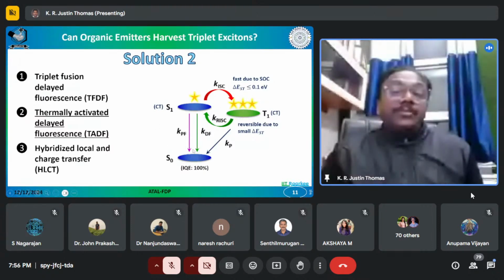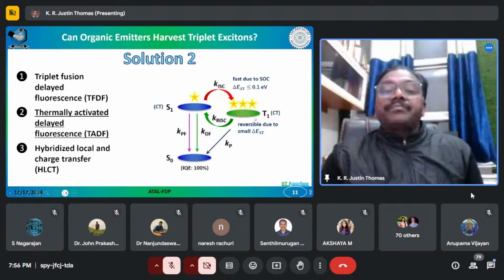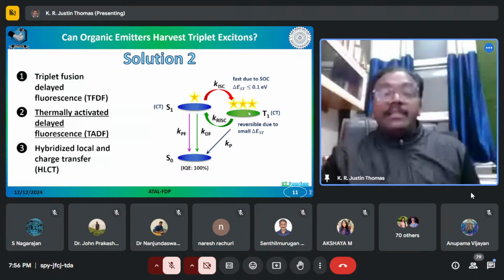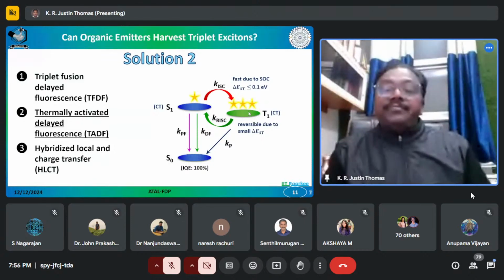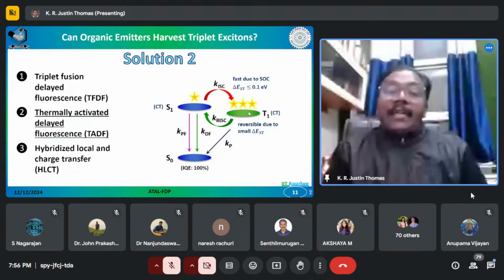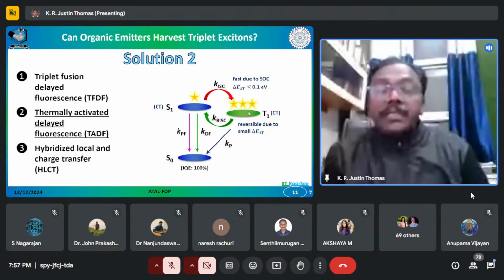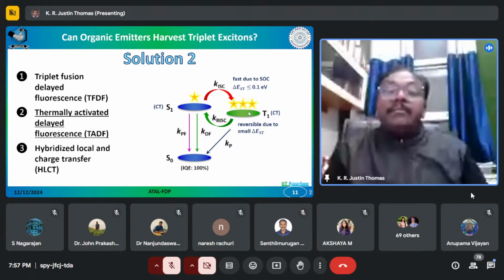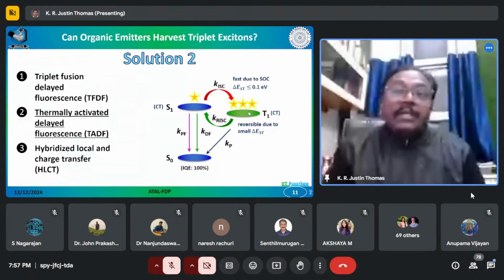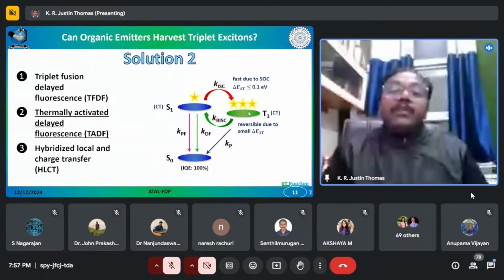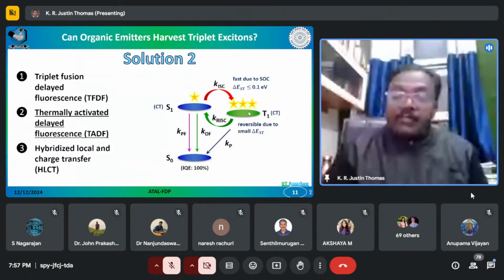And in certain organic molecules, it is observed that the singlet excited state is closer to the triplet excited state. It's an interesting observation. This happens when they have a well-separated HOMO and LUMO, which we will see shortly. That means the HOMO and LUMO are not overlapping. When the HOMO and LUMO completely overlap, you have a pi to pi star transition. When they partially overlap, you have a pronounced charge transfer. When they do not overlap, there is a charge transfer, but you will not be able to realize it in the absorption. That is what will happen.